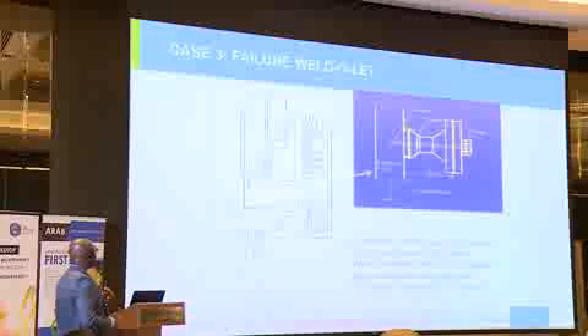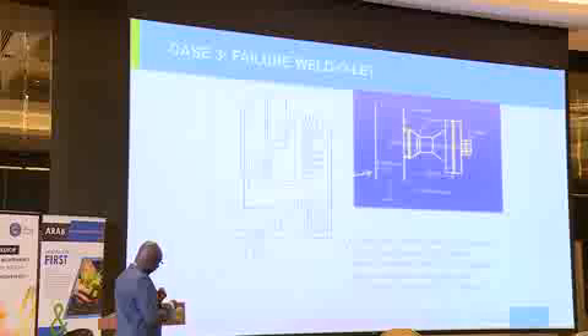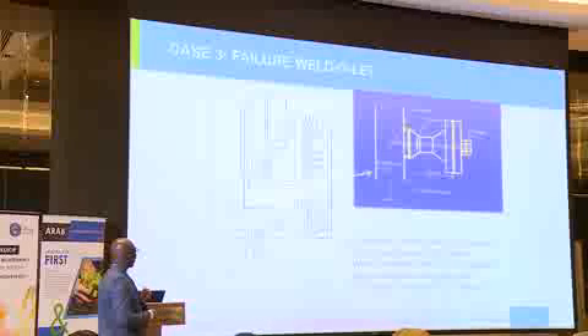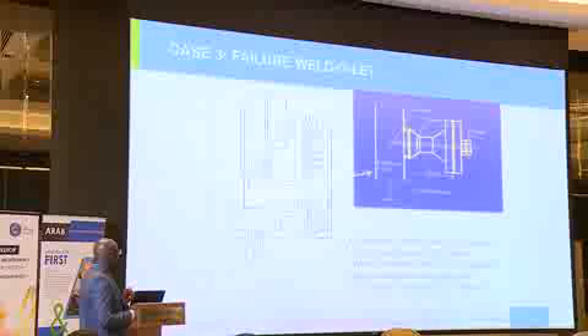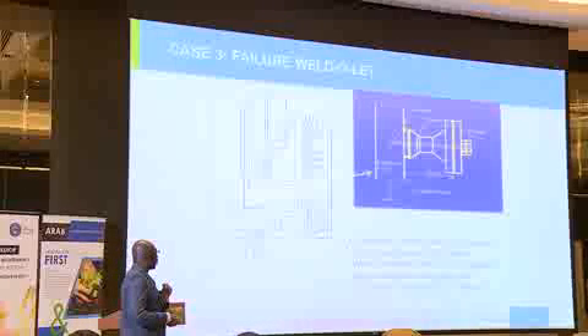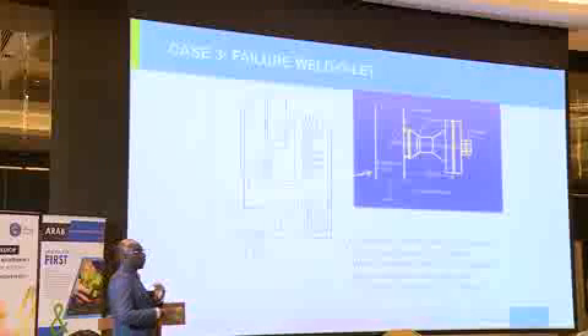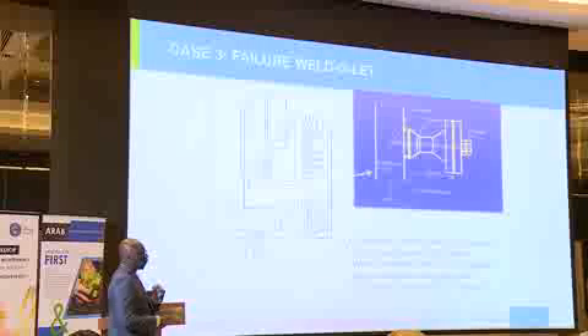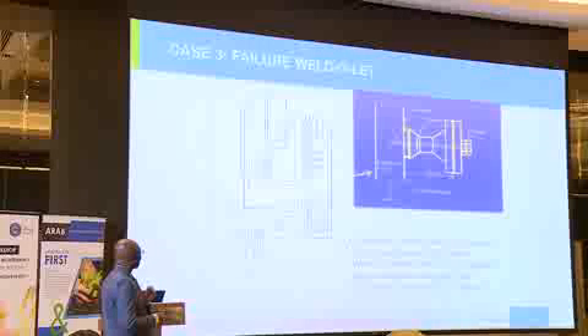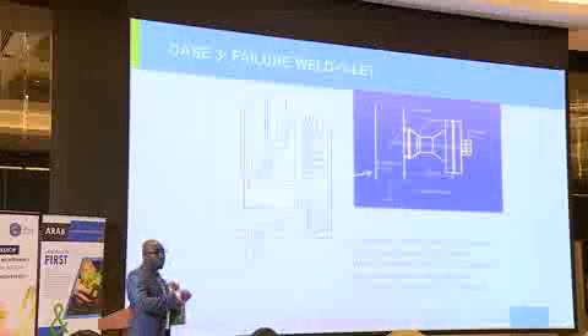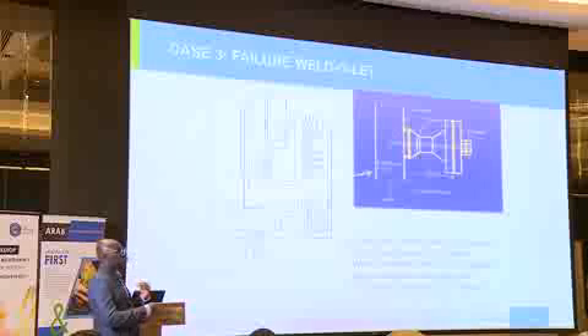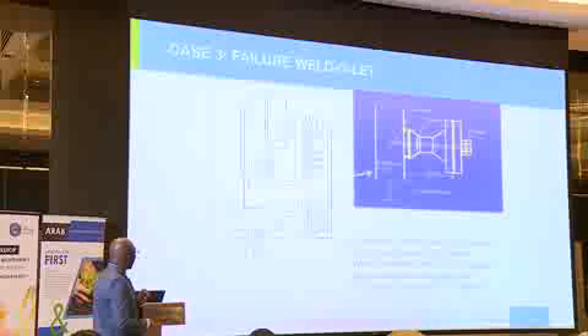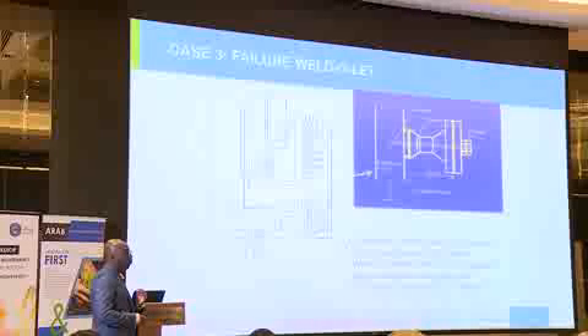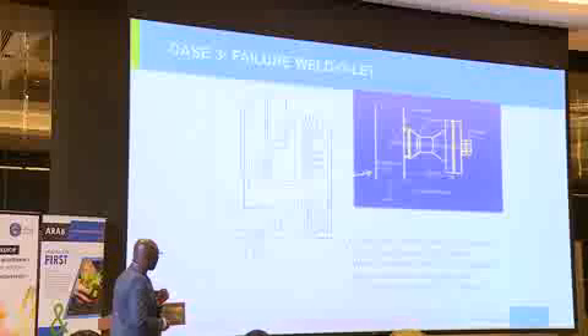This is the third case, and this case occurred on the reactor outlet line to the top of the stripper. There is a weldolet on this line. This plant had been running for 25 years. No attention has been paid to any of the process lines. But 2 weeks before a plant turnaround, it was realized that this weldolet for the thermal well was leaking at this point. There's a weld over here. And to avoid stopping the plant before the 2 weeks, it was decided to repair this weld on stream. Unfortunately, when they were repairing the weld, this weldolet ruptured, leading to several fatalities, which is quite unfortunate.